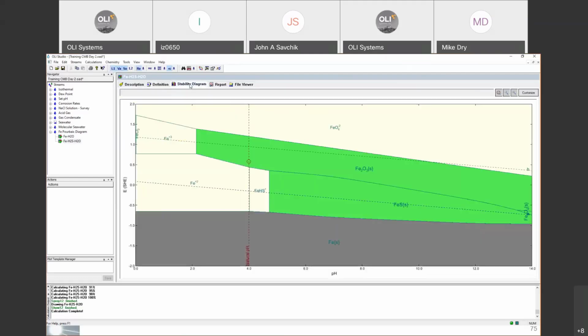Okay, so once you did that change here, you'll see that two things have happened. Notice that by adding more hydrogen sulfide, we are increasing the area of this iron sulfide area in here. We have decreased the hematite, the magnetite phase. You'll see not nothing, but a small amount of hematite is being formed, and everything else is iron sulfide.